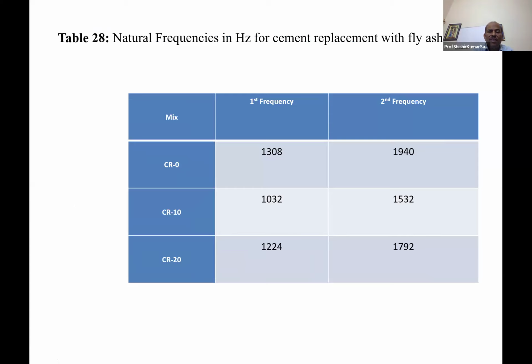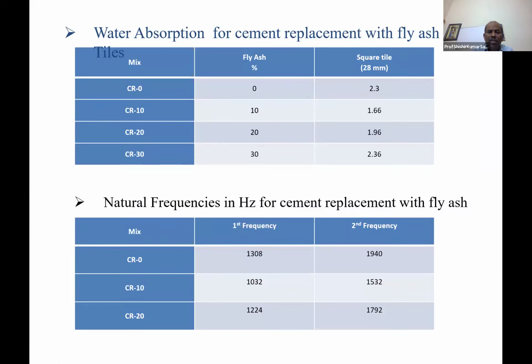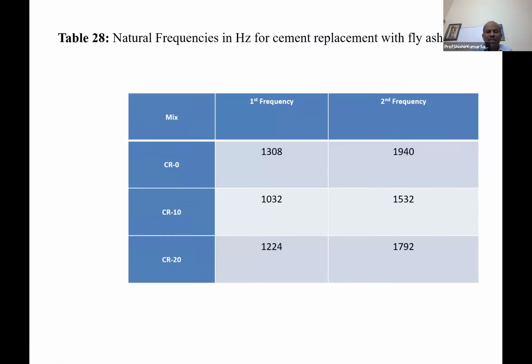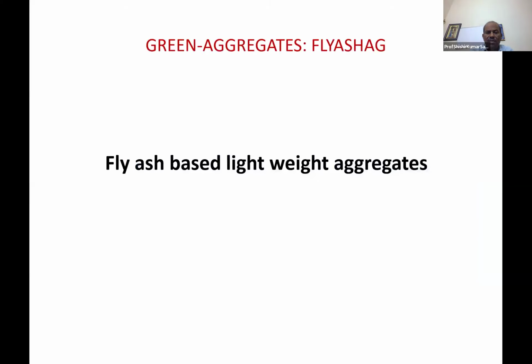Natural frequencies with cement replacement, this is with water absorption, this is with sand, this is with cement replacement. It's showing a trend of decreasing with increase of percentage of fly ash.